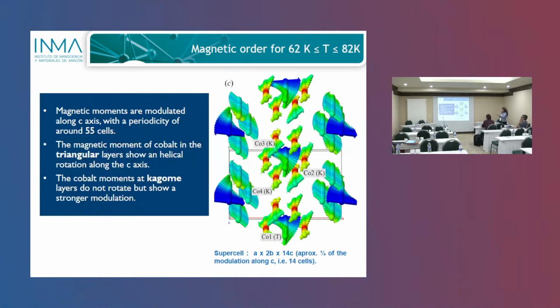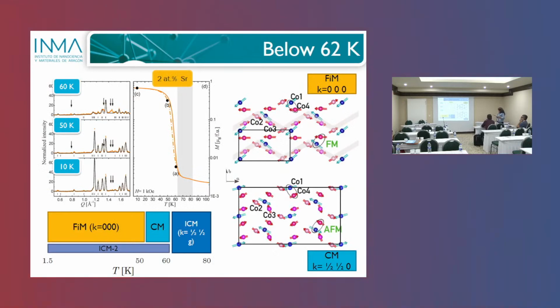And as I mentioned, you have different modulations depending on which layer of the structure you are looking at. But next, we had a look at what happened below that phase, below 62 Kelvin approximately. So first of all, if we look at the lowest doping level, you obtain at the lowest temperature the ferrimagnetic structure that I showed you in the beginning. But what happens in the middle between this incommensurate phase and this ferrimagnetic phase? In the middle, what we observe is that the incommensurate phase locks to a commensurate propagation vector.